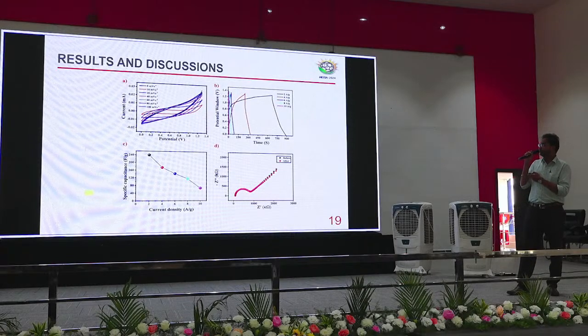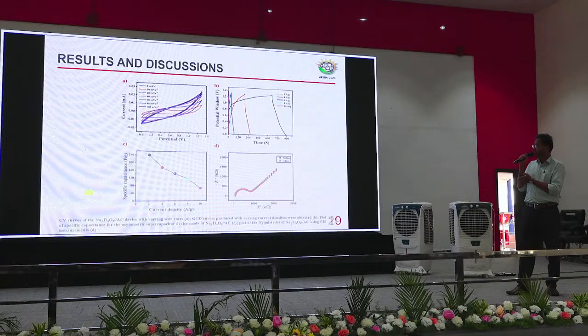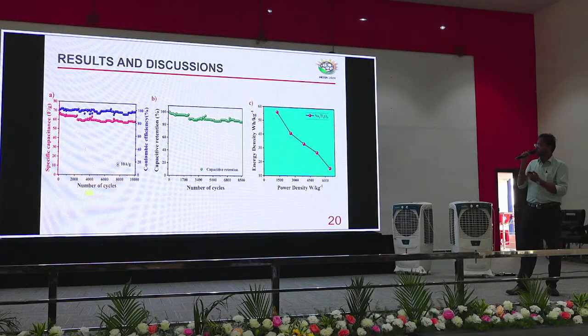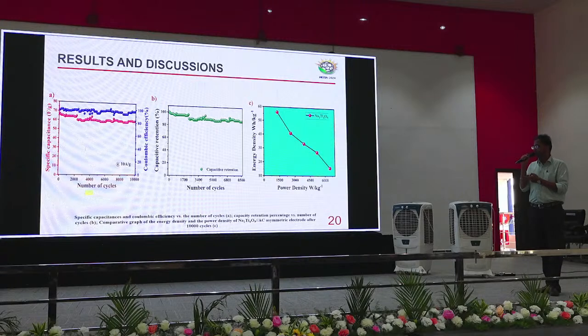The A figure denotes CV, and the B figure is the galvanostatic charge discharge studies at different current densities of 2, 4, 6, 8, 10, and then we have calculated from the B figure a specific capacitance around 245. In the C figure, we calculated the impedance studies before and after cycling. This is the rate capability study of the device, my coin cell. First the A figure denotes the capacity, Coulombic efficiency as well as the capacity retention. And then we have calculated the power density and energy density from the figure.